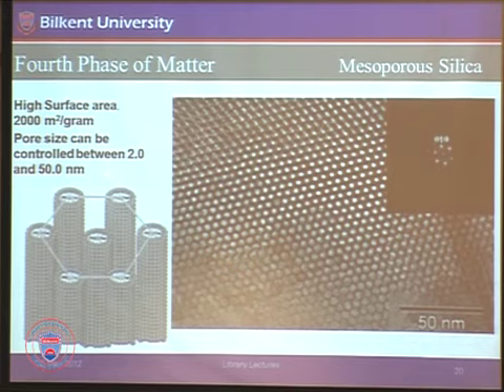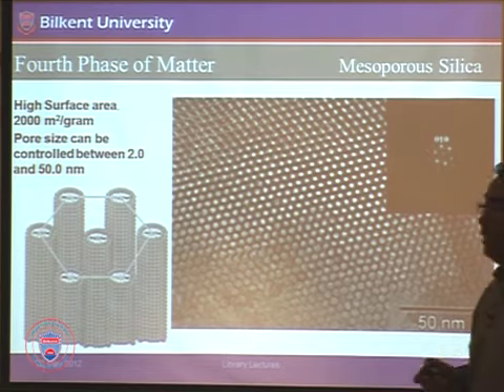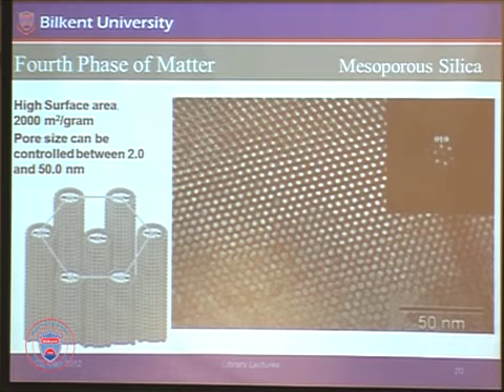You can go down to 2 nanometer here. Chemistry can do this for you, basically. These assemblies, you can modify these regions, solidify these regions. You get those solid materials in between those domains and burn the surfactant out because these are all organic. They can be easily burned out. You end up with a material with holes inside.